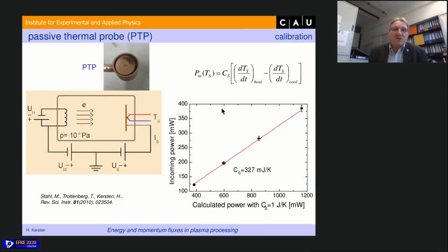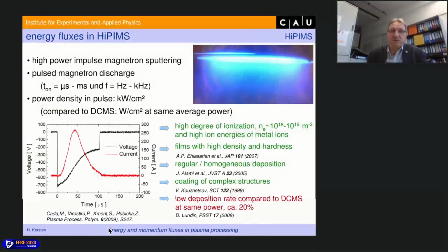different contributions. As I mentioned, to know the heat capacity of this thermal probe, we have to calibrate this, and we are doing this in a high vacuum chamber just by a heated wire. So we emit an electron beam, and there are no collisions on the way. And so we know that by the current and the voltage of this electron beam, which hits the probe, the probe is heated, and this is measured, and so we can calibrate the heat capacity of our probe, as you can see here. So this is important to get absolute values of the energy influx.